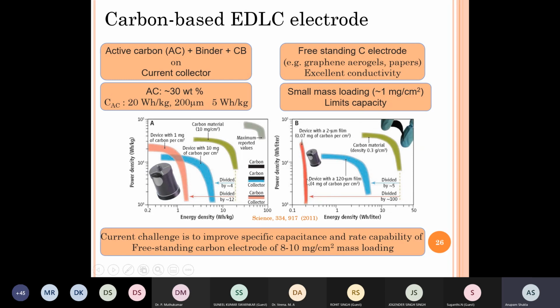However, this still provides better avenues for increasing the energy density compared to electrodes where the composition is active material, binder, conductivity enhancer, current collector. This is, by the way, the preferred and mostly available composition for commercial capacitors. The one on the right hand side is mostly in the laboratory.